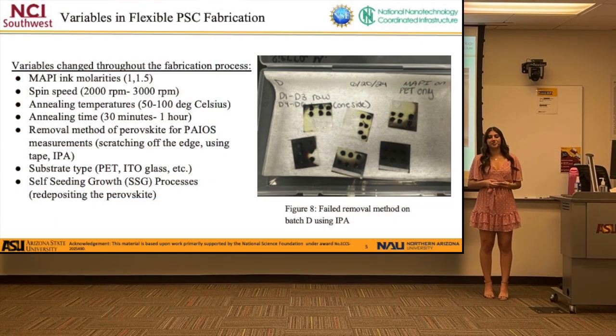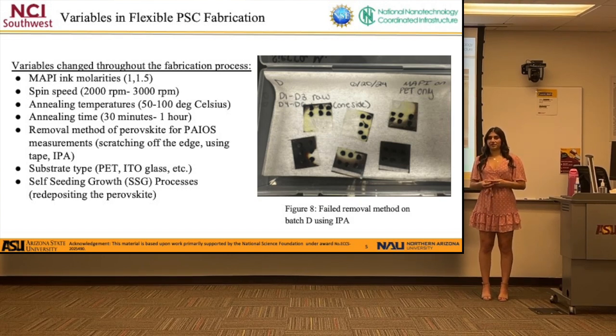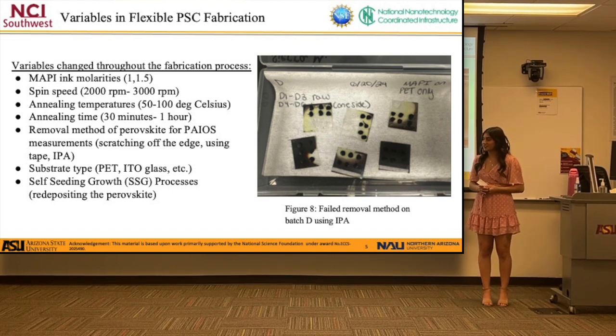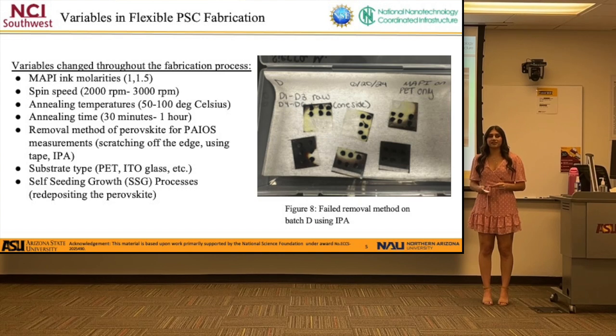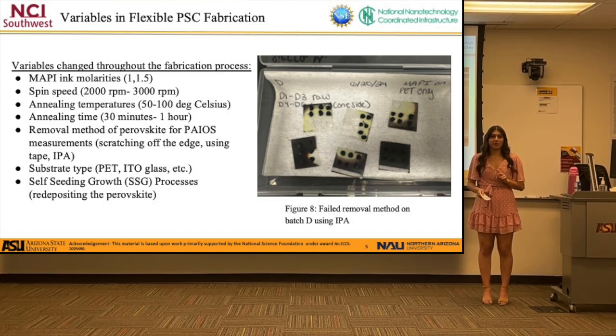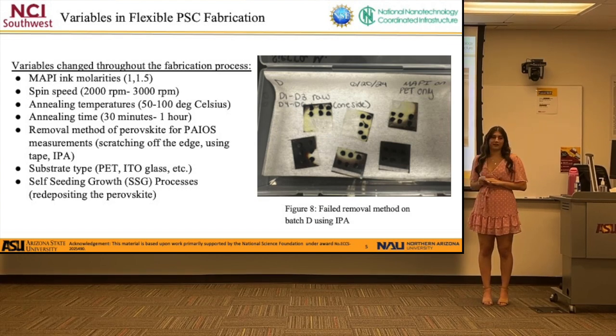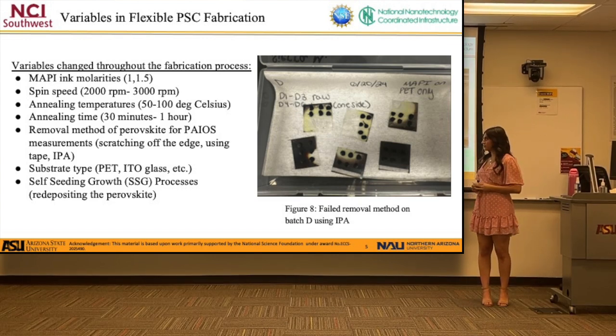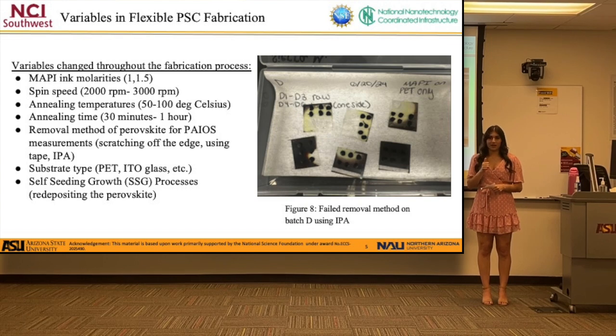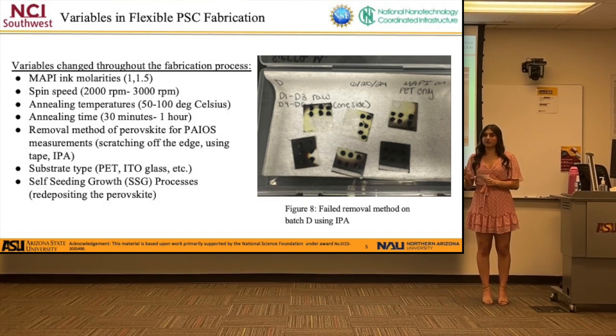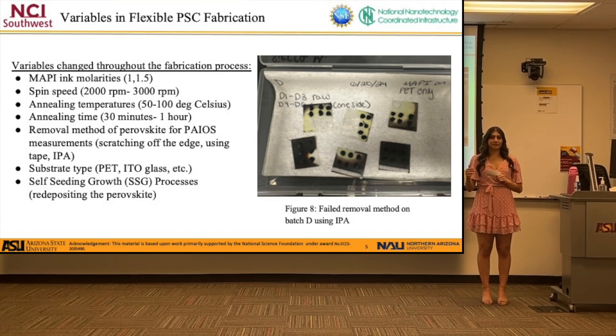So there were many variables that I changed within the perovskite solar cell fabrication, these were all the variables that I changed. I'm not going to list them all, but some of these things I used to thicken the film, modify the crystallization process, remove the perovskite in preparation for a later measurement that I'm doing. But I especially want to discuss the self-seeded growth process, which is essentially depositing the perovskite on the substrate twice in 2 separate spin cycles. So that was a new development that I found kind of towards the end of my research.